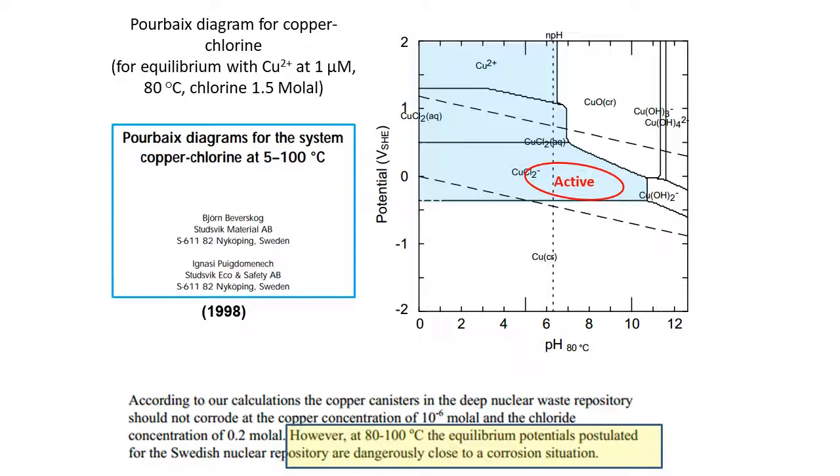So just to show this has been done, when some research was being done into can radioactive waste be loaded into copper barrels and sunk to the bottom of the sea, can this be done safely? A more complicated pH potential diagram needed to be researched, where all of the possible copper chloride complex ions needed to be considered, in addition to the copper phases without chloride that we considered in this diagram.